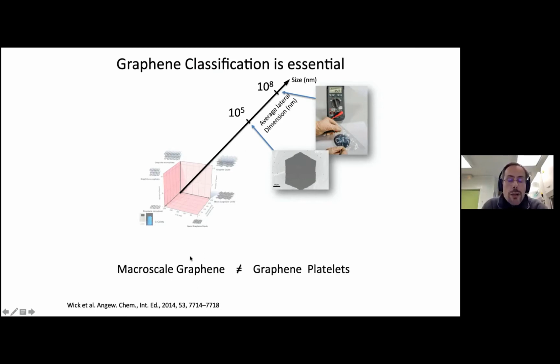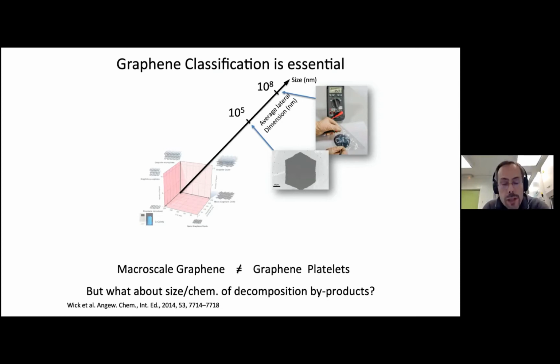So macroscale monolayer graphene is extremely different from graphene platelets and graphene flakes. So that's no surprise that the properties and the biochemical and the pharmaceutical property of the graphene in that case are very different from the other ones. So nevertheless, there is potentiality of decomposition, degradation of graphene in the body. And in that case, it couldn't come back inside this space, even though it starts from that. So it's very important to know about the decomposition and the byproduct of graphene and the potential toxicity of it.